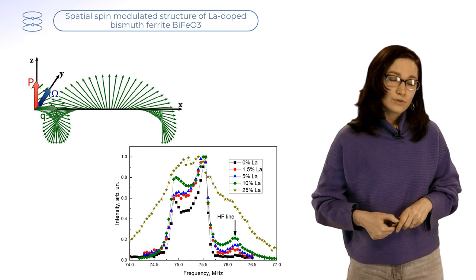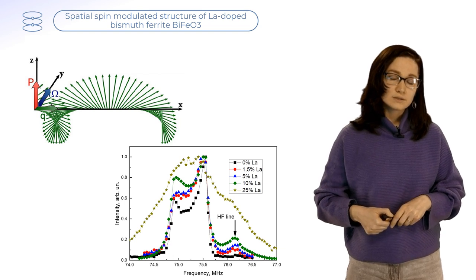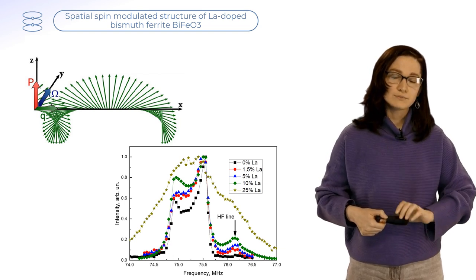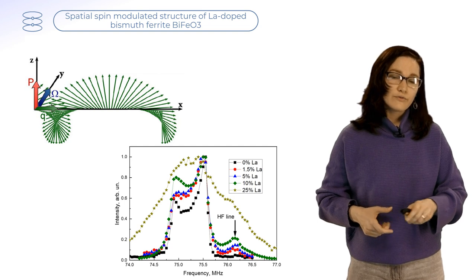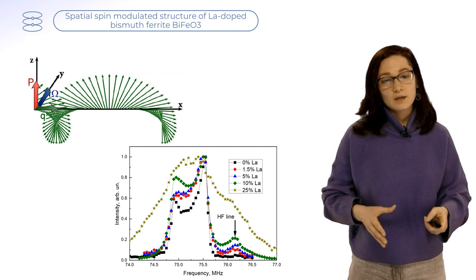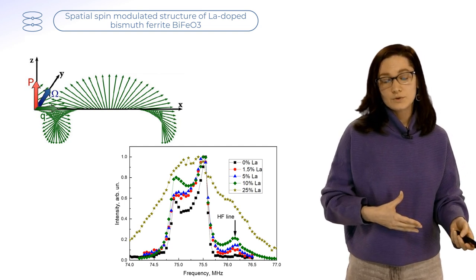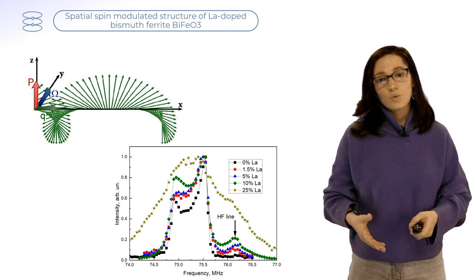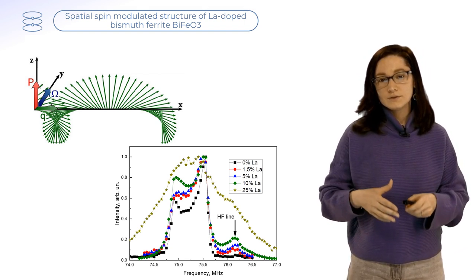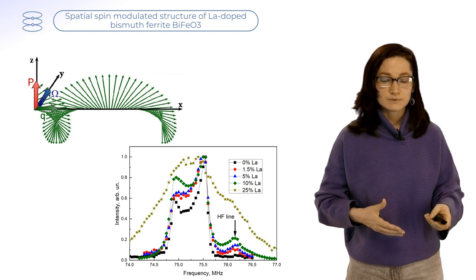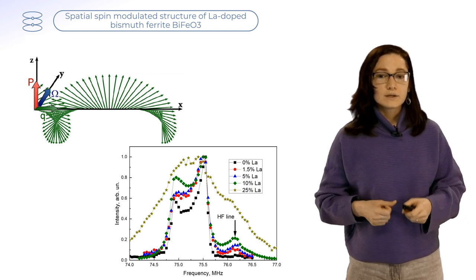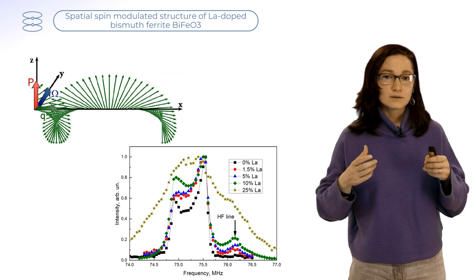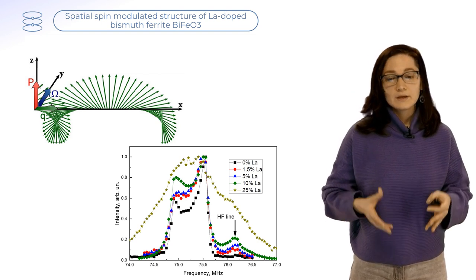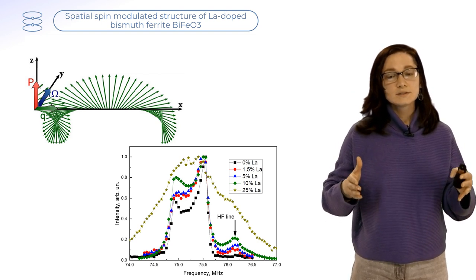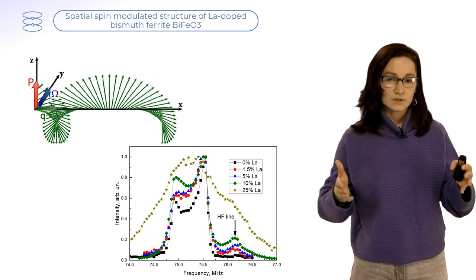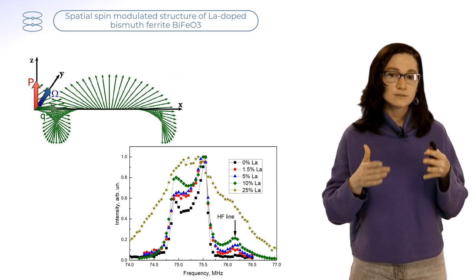We have found the high field line. It lies to the right of the main spectrum, never found by other methods, and we connected it with the iron atoms which are located in the neighborhood of doping atoms. And we can see that the spatial spin-modulated structure gives us the specific shape of the spectra. It's the two peaks and steep slopes.